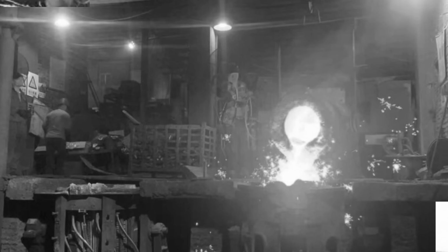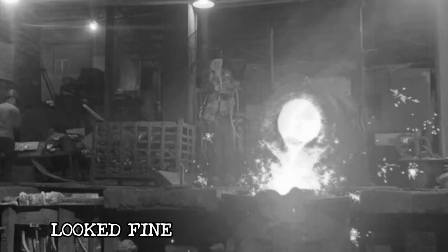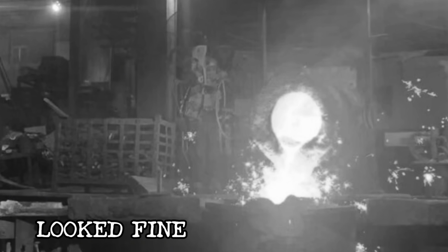The worst part? You couldn't see the danger coming. The ladle looked fine. The support brackets looked fine. The refractory lining looked fine. But microscopic cracks were forming. Metal fatigue was accumulating. The thermal cycling, heat, cool, hundreds of times, was weakening the cast iron. And nobody was checking. Nobody was measuring. Nobody was calculating the safe operating life of a ladle support bracket because that science didn't exist yet.